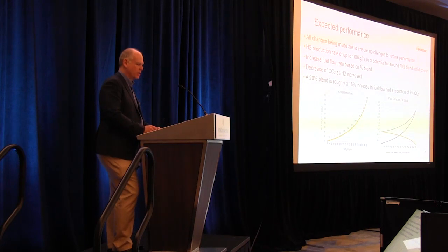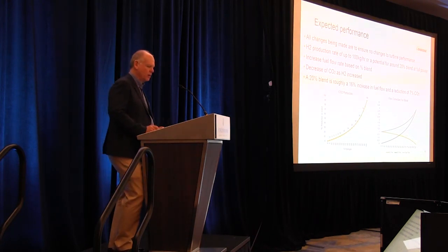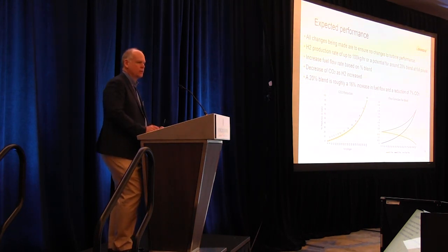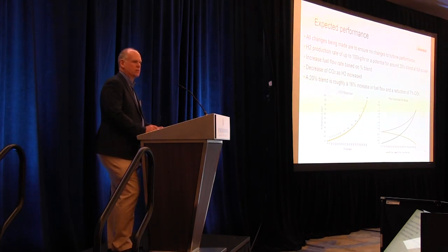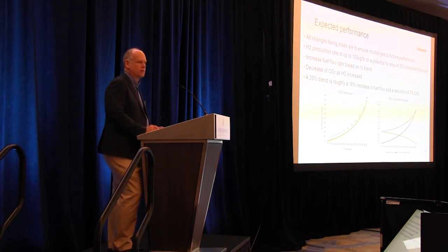So we're looking at a hydrogen production rate of up to 100 kilograms per hour, or potential for about 20% blend at full power. And it does increase the fuel flow rate, like I said, so that has an impact on the fuel gas skid. It decreases CO2 as the H2 is increased. So a 20% blend, which is our target, is roughly a 16% increase in fuel flow, volumetrically, and a reduction of about 7% of CO2. I don't have NOx on here. There's a little bit more uncertainty around NOx, but the NOx is not expected to increase and potentially decrease slightly as well.